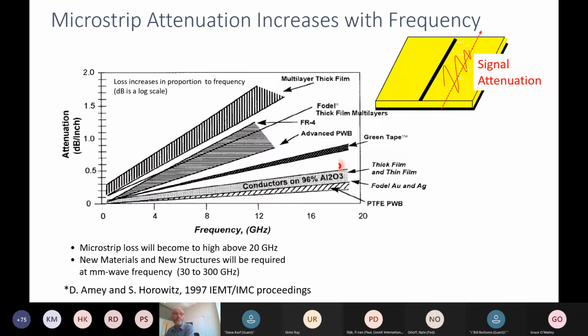If we just take one example, where we were looking at low temperature co-fired ceramics, in this case we were looking at the attenuation in terms of dB per length. And here's the frequency, and it's pretty evident that as we push to these higher frequencies that I mentioned for the millimeter wave, this will get very high. Remember, dB is a log scale, so this is really increasing rapidly as we approach those frequencies that we were talking about for 5G. And the other thing that's really interesting with this plot is that we have a comparison of different dielectric materials. FR4 shown here, some Teflon base or fluoropolymer shown here, and then some ceramics.